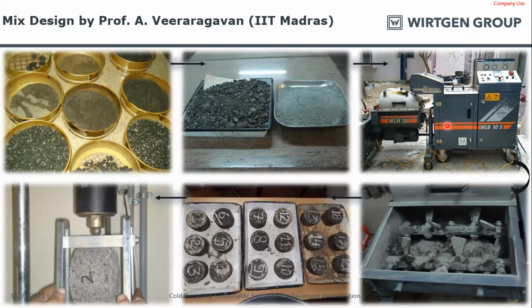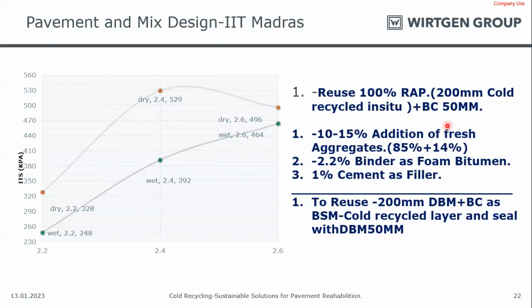The minimum criteria as per the codes is that we need to get a half-life of greater than 6 seconds and an expansion ratio greater than 8 times. This should be satisfied as per the TG2 guidelines 2009. Then we cast molds and check for ITS, indirect tensile strength. This is done to check the susceptibility of the binder coating to moisture damage. As per IRC 37, the minimum criteria for ITS values are an ITS dry value of 225 kilopascal and an ITS wet of 100 kilopascal.